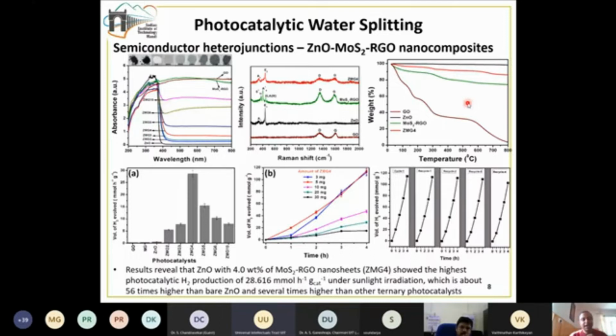Then we did these photocatalytic hydrogen evolution experiments under direct sunlight for all the samples that we have prepared. And to our surprise, we found that one of the samples, the ZMG4 sample, having 4 weight % of MoS2 and RGO, gave the highest amount of hydrogen evolution. And this is very interesting. The hydrogen evolution is very good, about 28.616 millimole per hour per gram, which is a very high value in comparison to several other examples reported in literature. So this is something which is very good.